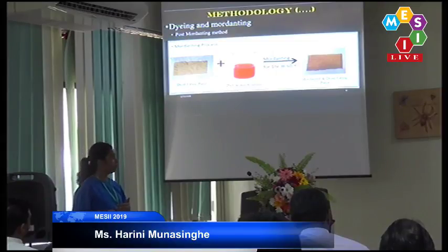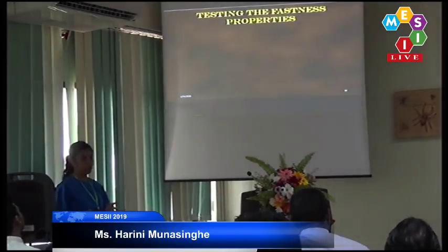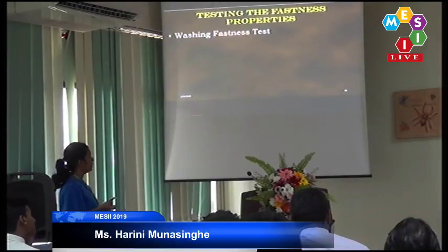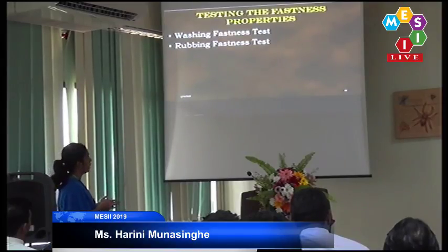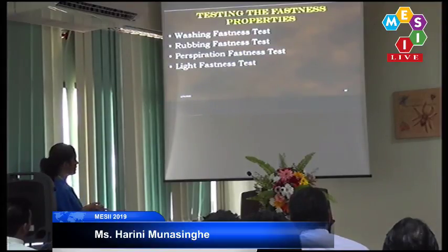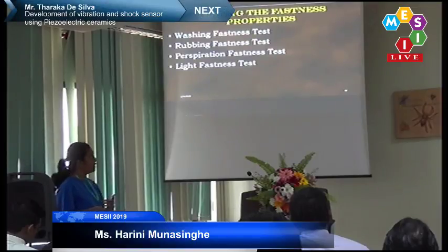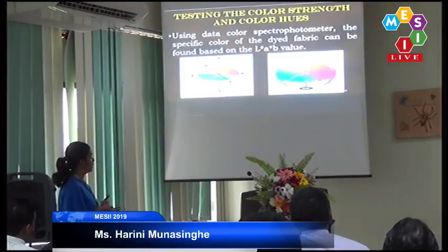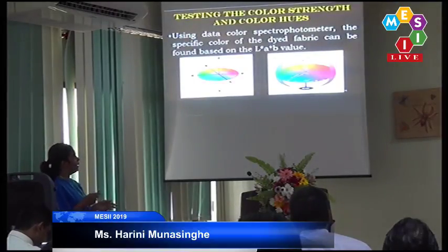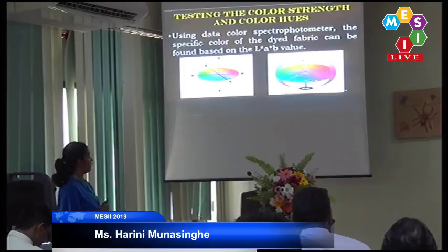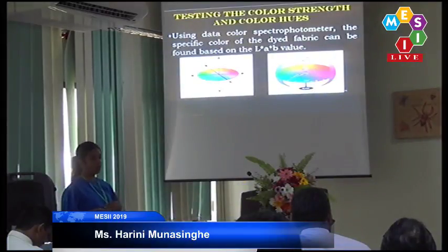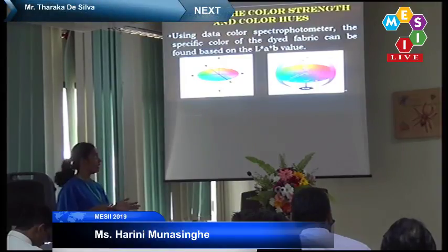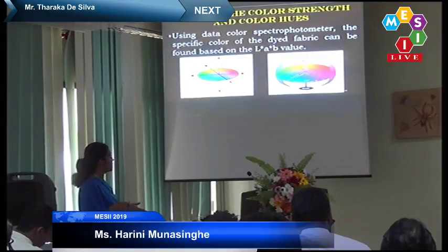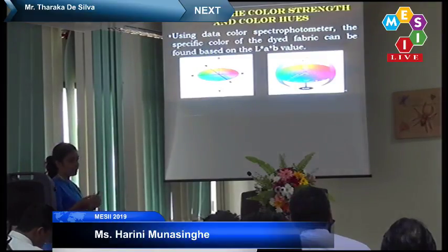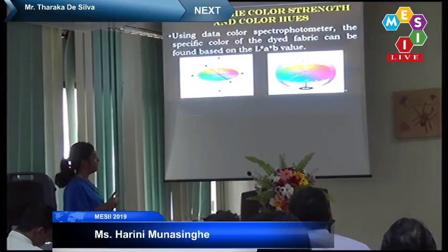After the dyeing and the mordanting process, we need to test the fastness properties of the dyed fabric piece. For that, we tested the fastness properties of the dyed fabric piece using ISO standard methods for the washing fastness test, rubbing fastness test, perspiration fastness test and light fastness test. After testing the fastness properties, we tested the color strength and the color hue values of the dyed fabric piece using a Datacolor spectrophotometer. The specific color of the dyed fabric can be found based on the LAB color coordinate value. This LAB color coordinate value is similar to an XY coordinate. Using this plate and this sphere, we can get the specific color for that dye using this LAB color coordinate value.